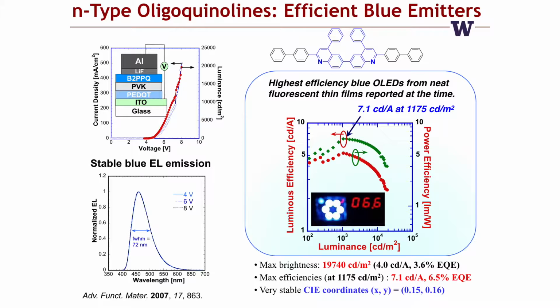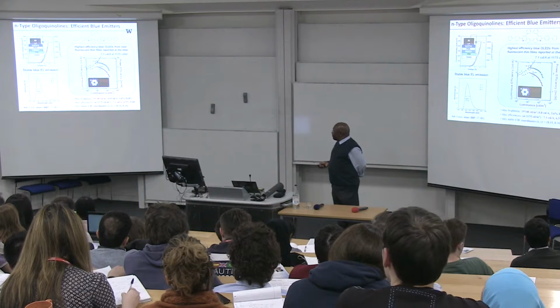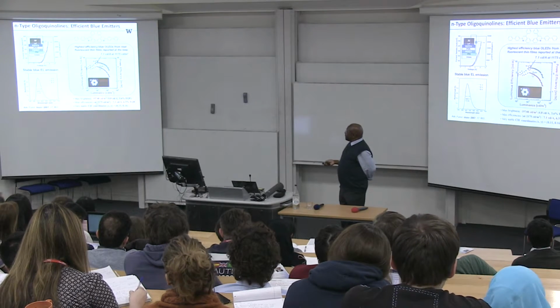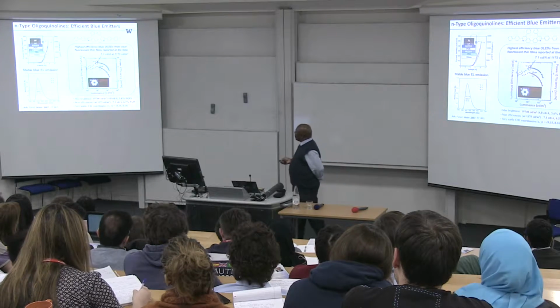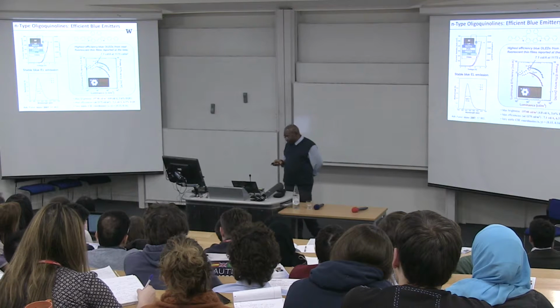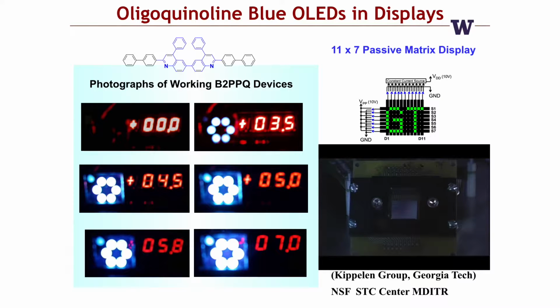All right, so we made devices in our lab. This is a typical structure of the device, and you apply voltage, and then you get blue emission from that, as you can see here. They can be very, very bright, as seen here with a picture of pixels of the devices, and quite bright. And at the time, they were the most efficient blue OLEDs.